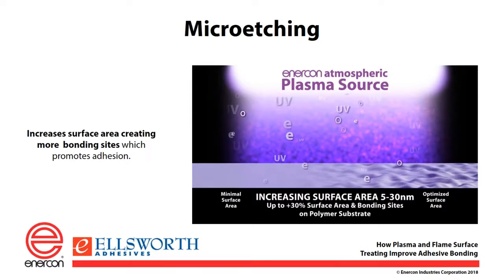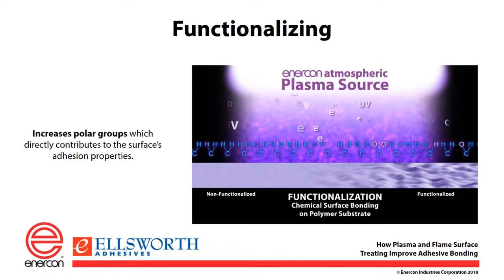The second thing it does is microetching. This was mentioned earlier by Greg about giving more bonding sites. So on the left side here, you have minimal surface area, and after you've treated the surface, you can see that you've got much more surface area with which to bond. So if you've got adhesive there, it gives it more bonding sites. And the third is functionalization, and that is where we're actually changing the surface and adding groups, hydroxyl groups, carboxyl groups, oxygen groups to the surface, which actually does increase the surface energy so that you have better bonding sites.